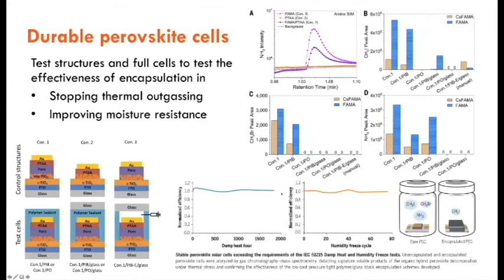With the humidity freeze test, there's a prerequisite thermal cycling where you've got to thermal cycle the cells between -40 and 85, 10 times. And then you freeze the cells very quickly to -40 in humid conditions. So basically you deliberately have condensation. So if there's any water within the cell or within the encapsulating material, it will form crystals and wreck the encapsulation. So the requirement is 30 humidity freeze cycles, and we managed to exceed that by almost 3 times.